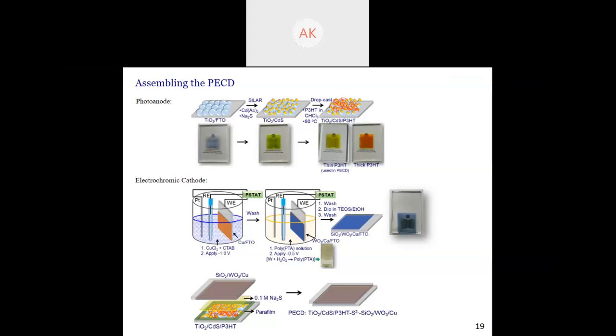So why electrodeposition? Because in electrodeposition, you can expose the substrate to a very wide region. So you can deposit the material over a long range and at a very high surface area in a very small time. Finally, when you fabricate the PECD, you have TiO2, CdS, P3HT, you have 0.1 molar Na2S, and you have SiO2 WO3 Cu as your counter.